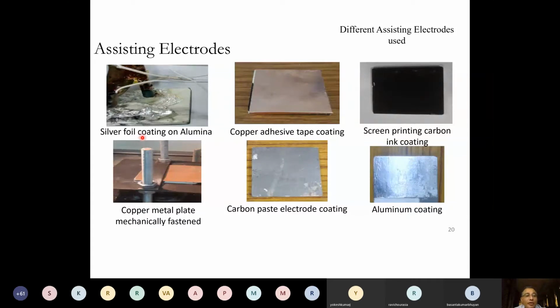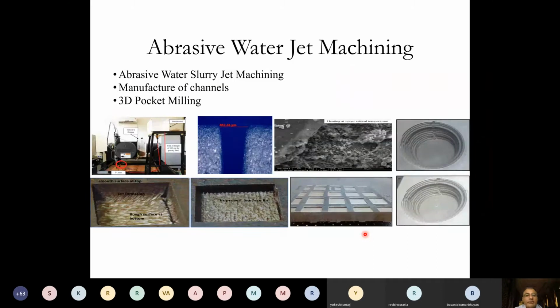So this is putting a silver foil coating on alumina to generate the first spark, a copper adhesive tape coating on the alumina, screen printing carbon ink coating, aluminum coating, carbon paste electrode coating, and a copper metal plate which is mechanically fastened. The white one is ceramic, and the copper plate was mechanically fastened to the alumina to generate the initial set of sparks. Copper being metal, this led to ultimately transfer of sparks to the alumina, and the alumina was also burned.